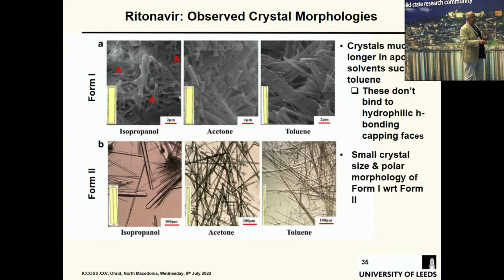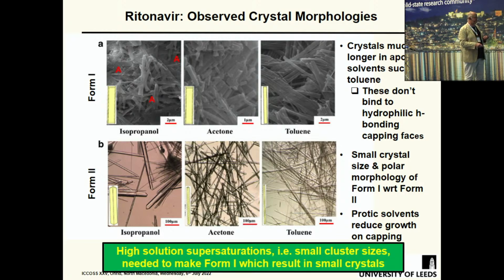Small crystal size and polar morphology for form 1. Look, these are 2 microns, this is 100 microns. In order to get this, you basically reflect the fact that you need a high supersaturation to get form 1, and that pushes the nucleation rate up, and that pushes the crystal size down. High supersaturation and small cluster size are needed to make form 1, which results in small crystals.